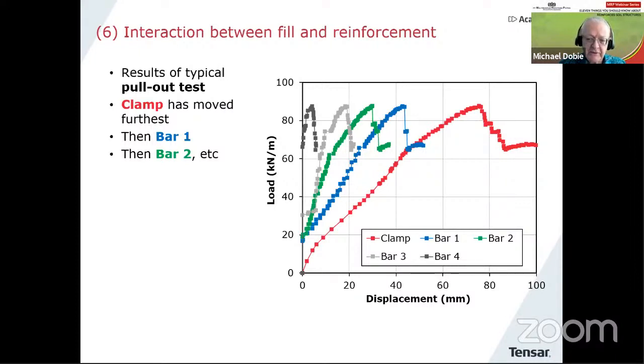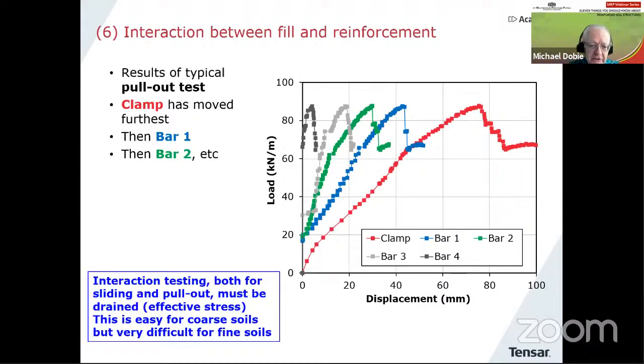It extends. So this actually makes pull-out testing quite complicated and sometimes quite difficult to interpret. But that's what a typical result can look like, especially when the pull-out is incomplete. For pull-out tests to work well, you need to have quite short pieces of geogrid, especially if the normal stress is high. Otherwise, you simply can't pull the material out. Anyhow, I thought I would show you one important point here.